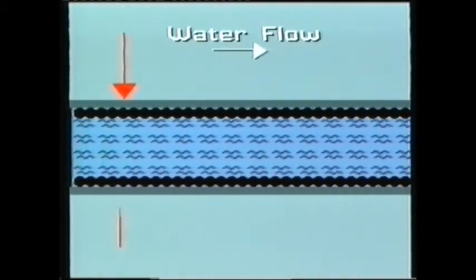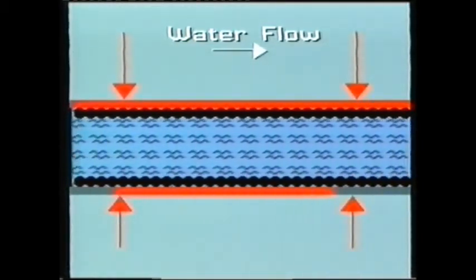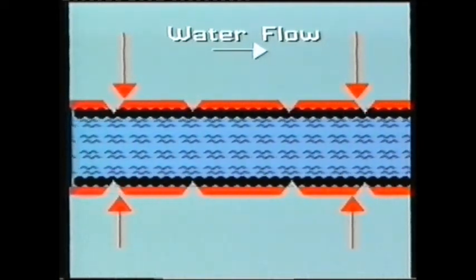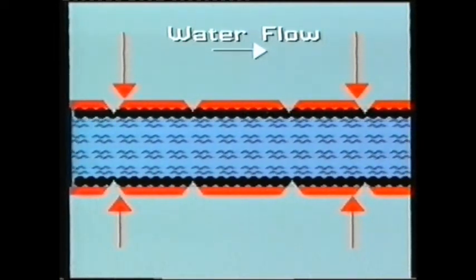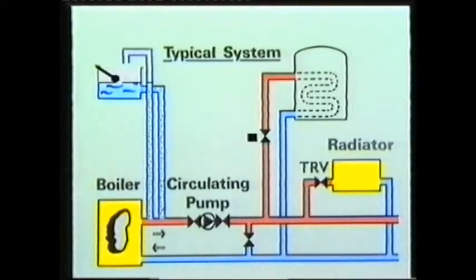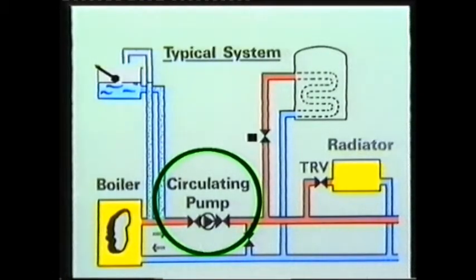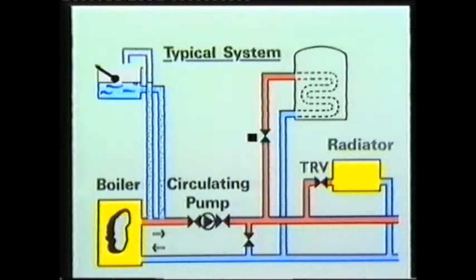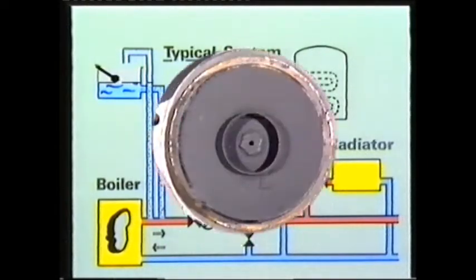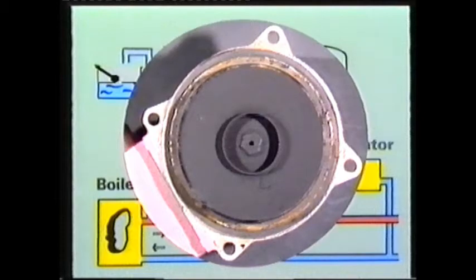This is because heat transfer is reduced by a build-up of sludge and scale, which creates an insulating effect. Eventually the boiler is likely to overheat and fail altogether. Here are some more clues. Equally vulnerable is the pump. Black oxide sludge, being abrasive and magnetizable, is attracted to the shaft and bearings in modern canned rotor pumps. This is the most common cause of circulating pump failure. It leads to shaft and bearing wear, and eventually the pump will seize as this one did.